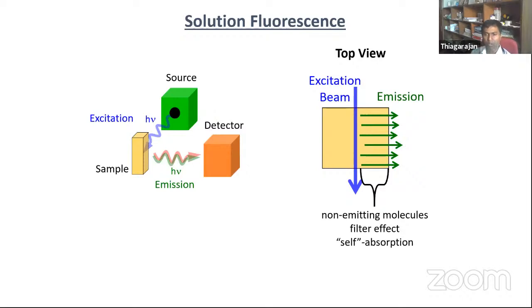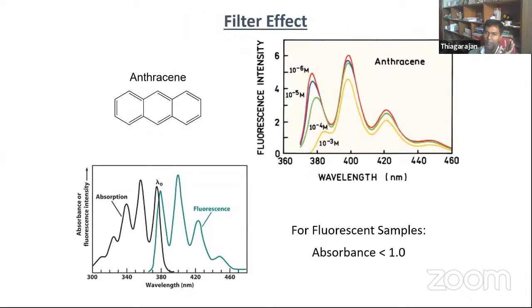When we excite the molecules, not all the molecules go to the excited state. Only a few molecules go to the excited state. When they emit a photon, if you have too many molecules in the solution, the molecules neighboring the emitting molecule absorb the light. For example, if we excite 100 molecules at high concentration, we get emission from only 30-40 molecules. If we have very low concentration and excite 100 molecules, we get emission from more than 60% of the molecules. So we have to take care of self-quenching. We call this the inner filter effect.